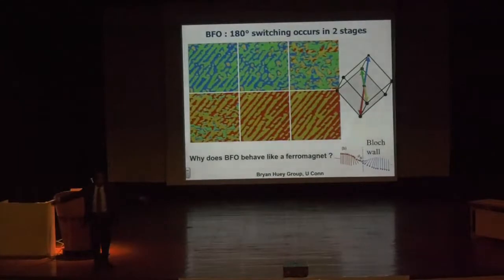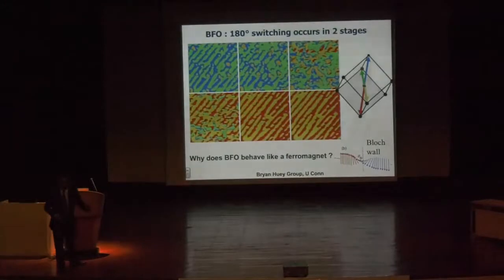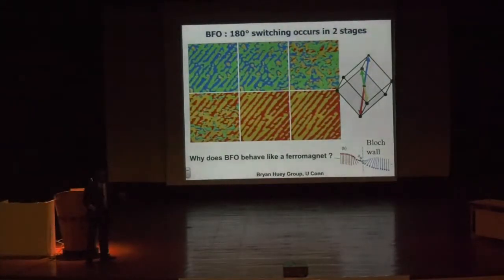They're rotated by 71 degrees from each other. So the greens and the blues have a 71-degree rotation in the polarization. You can then apply an electric field and map out, with time resolution of the order of microseconds, what happens to the polarization. And what we found was that essentially they go from like this to like this. Each one of the domains rotates by 180, but the neighboring one is 71 degrees apart.